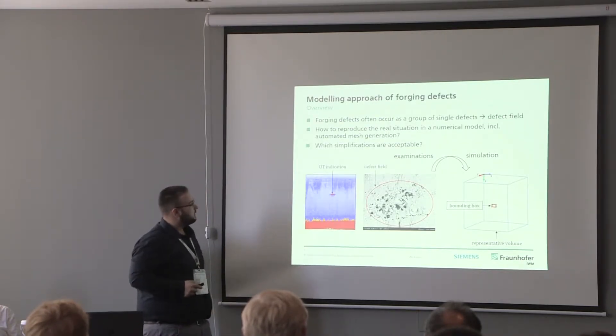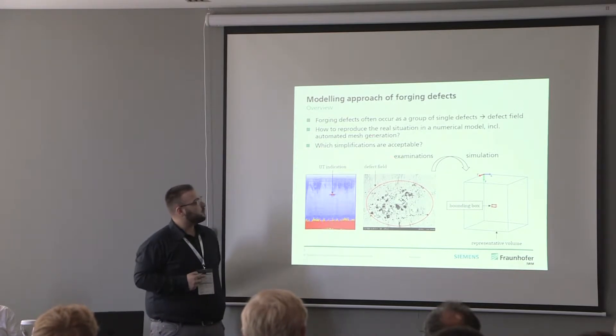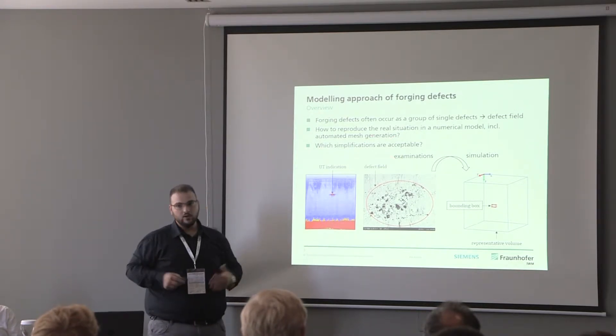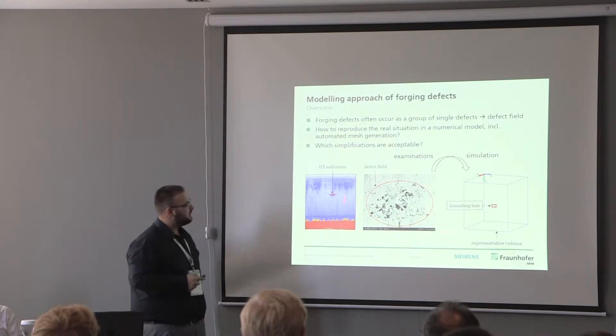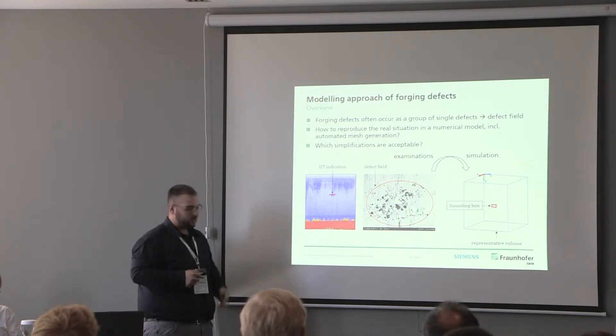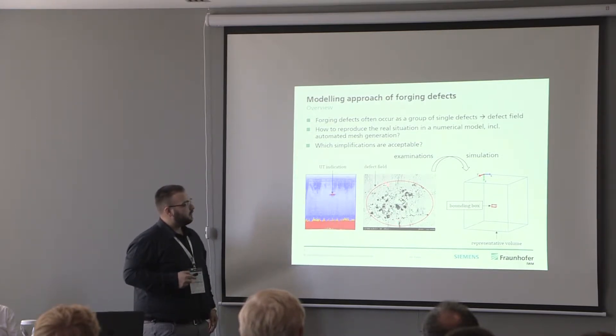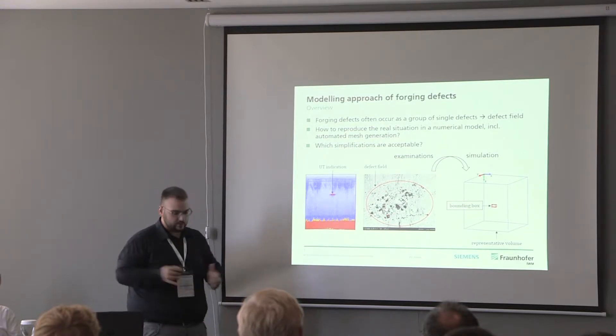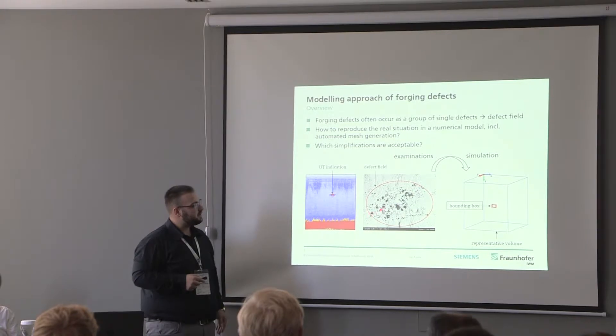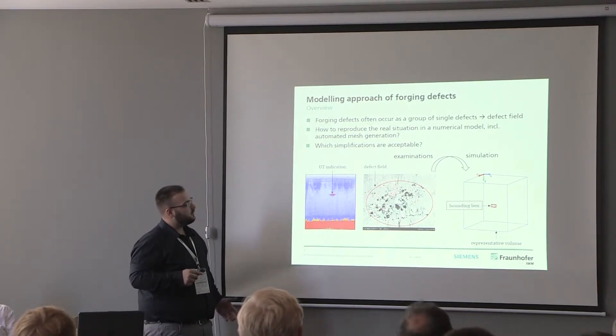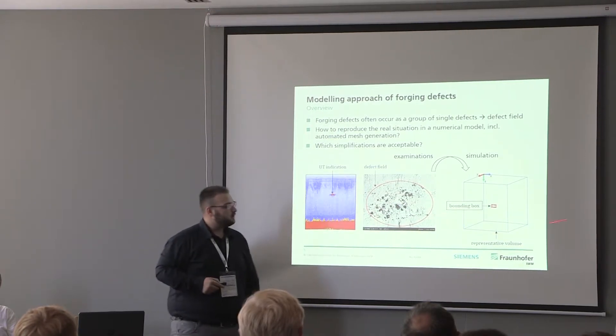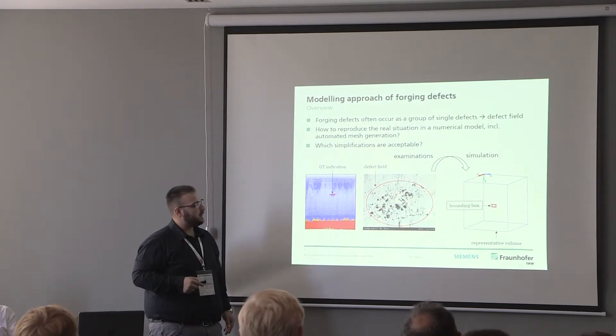How did I do this? With an algorithm. There are two main questions: how to reproduce the real situation in a numerical model, including automated mesh generation, and which simplifications are acceptable. We take specimens from UT indications and test them under LCF conditions. A colleague determined statistical distributions about the defect size and the distance between defects, and I put them into the simulation model to model the defect field in an automated way.